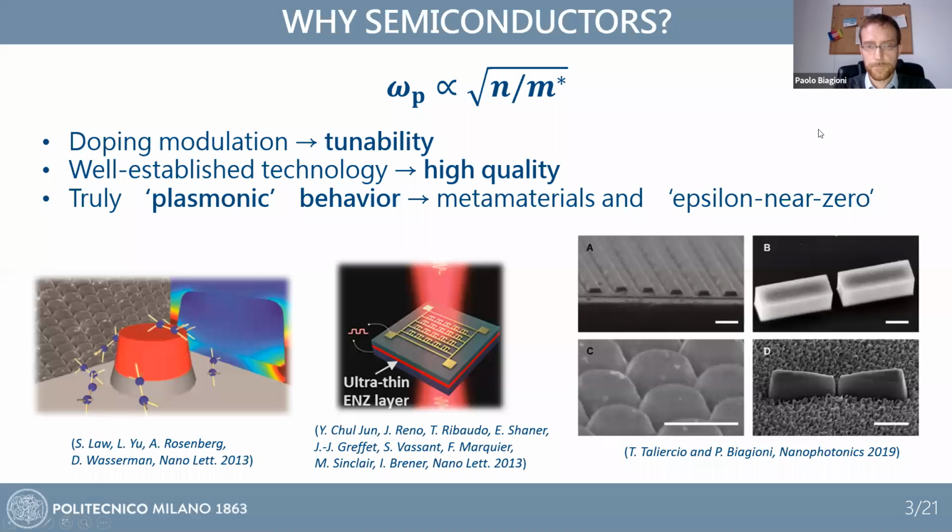Yes, we have, and it increases indeed, and it's quantified. But I think that the answer to this question should first stress one point: if you consider the scattering rate by itself, or if you consider the imaginary part of epsilon by itself, this does not tell you much about how good your plasmonic performance will be. Because if you have a higher doping and you have a higher plasma frequency, you don't only have